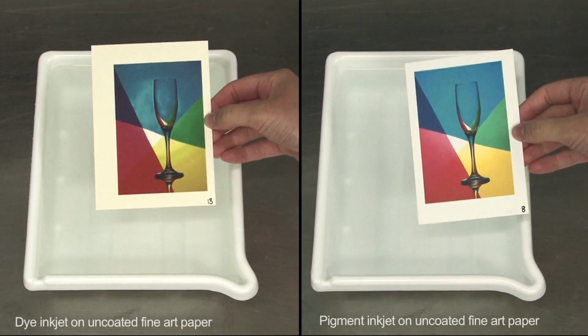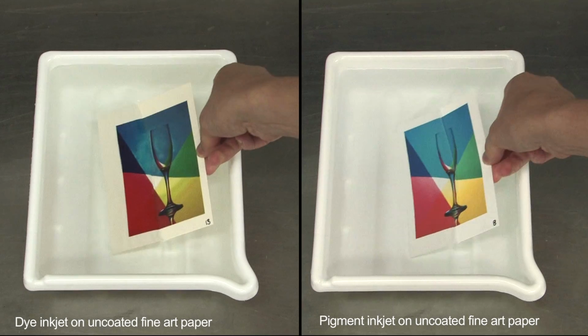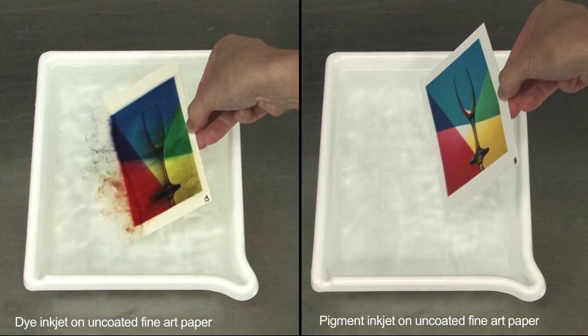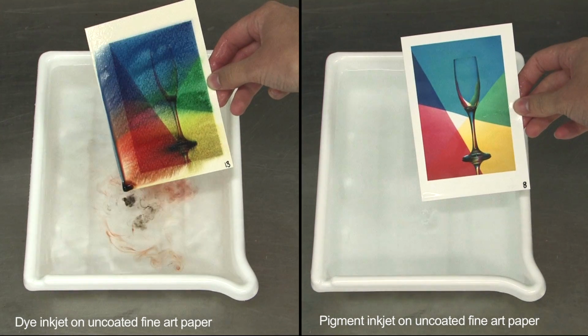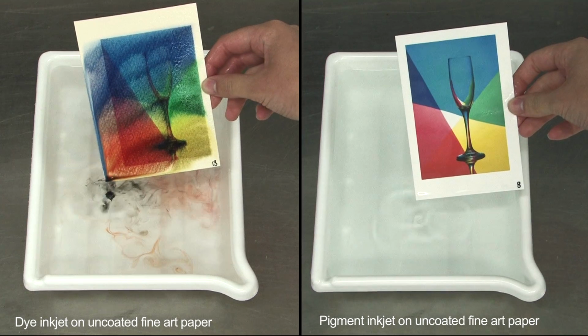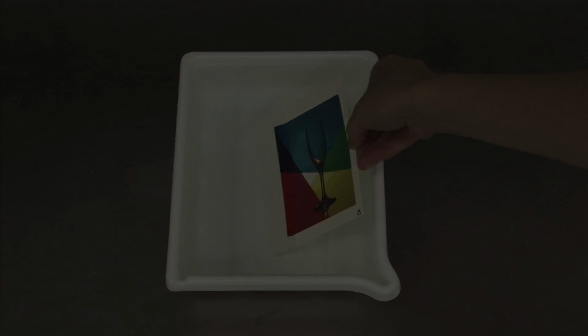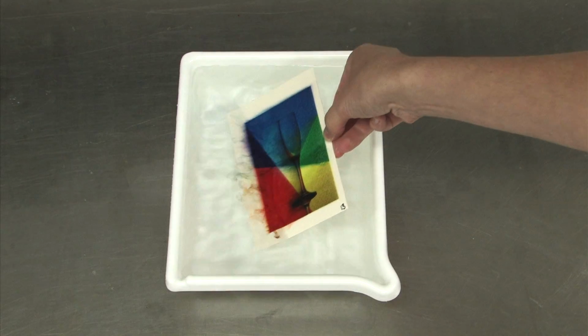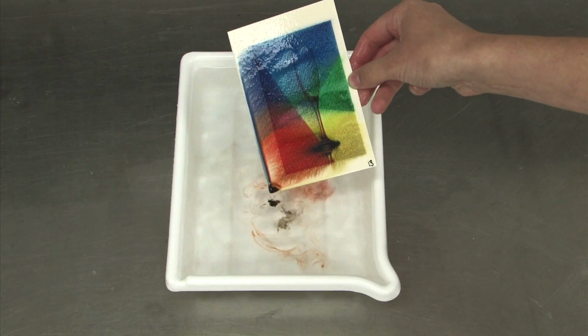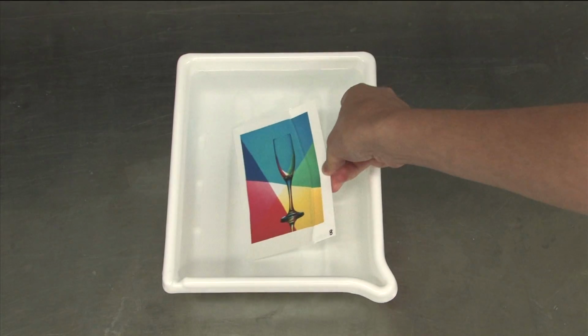These two prints were created with uncoated fine art papers. The sample on the left was made with an older iris dye printer, while the sample on the right was printed with a newer pigment printer. The iris print instantly bleeds, totally ruining the print, while the pigment print does not bleed at all.